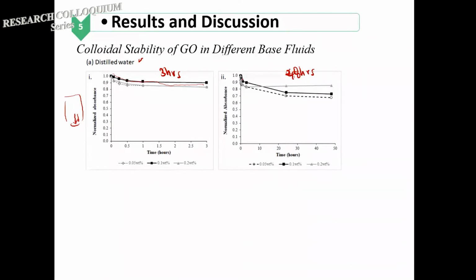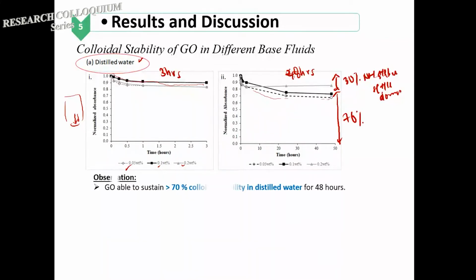By prolonging the duration to 48 hours, you will see some of the nanoparticle further settle down and become unstable. However, about 70% of the nanoparticle is still stable. About 30% is not stable and starts to settle down. We're working on different concentrations, and it seems the concentration doesn't have a very big impact. So based on the result here, we found that graphene oxide is able to sustain more than 70% colloidal stability in distilled water for about 48 hours.